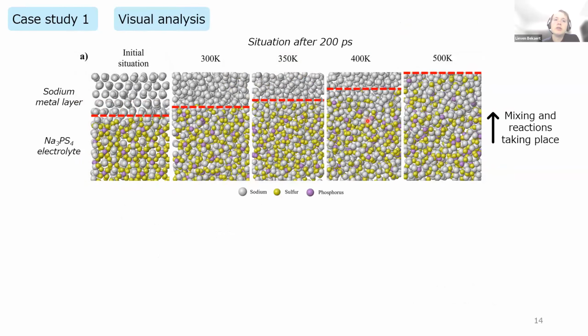So the first thing that we can do is to perform a visual analysis. As you can see, in the beginning we have a very clear distinction between the electrode and the solid state electrolyte. And over time, you get this interface. It starts to move upwards as sodium starts to mix into this solid state electrolyte and also starts to react. But it's very difficult to actually see what happens.